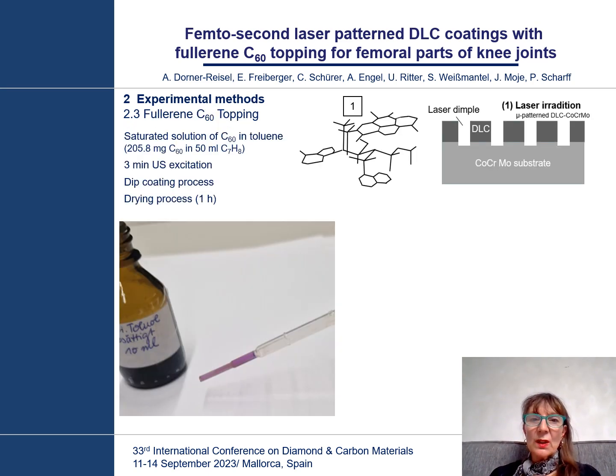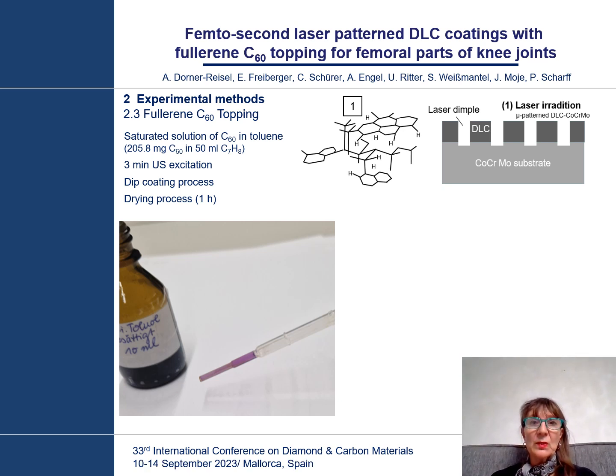The schematic drawing number 1 shows you the typical microstructure of diamond-like carbon, where there are sp2 hybridized and sp3 hybridized fractions, as well as voids. And in these voids, hydrogen can be trapped. Such coatings have a high level of compressive residual stresses.